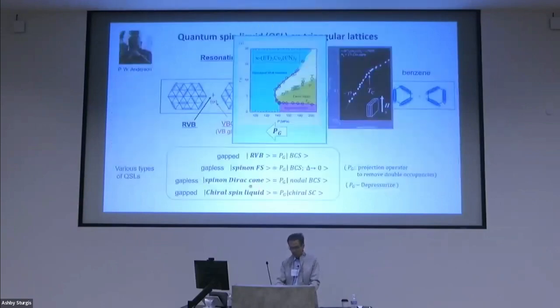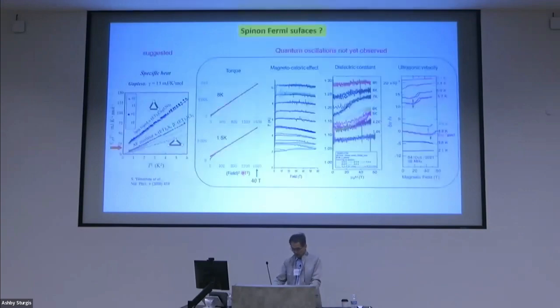There are many theoretical proposals for the spin liquid state. One interesting state is a spinon Fermi surface. Indeed, such a state was suggested by the finite linear-T gamma in specific heat. However, we searched under conditions up to 60 Tesla. Torque, magnetostriction, dielectric, and ultrasonic measurements did not show any quantum oscillations. So to date, we have no fundamental indication of the Fermi surface.